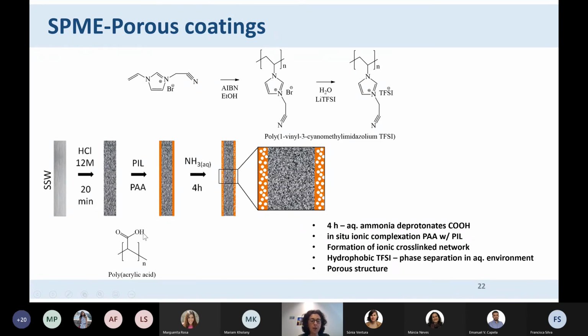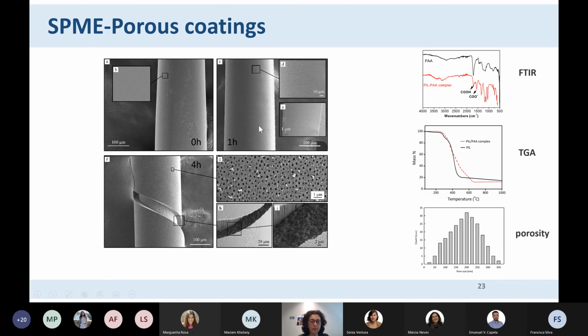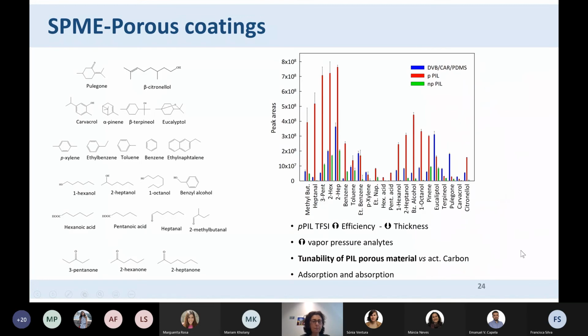And what we did was we ionized the polyacrylic acid, so it cross-linked with our PIL. And at the same time, the one that was not cross-linked was washed out by the solution, leaving us with pores. So here we have the different times that we had the wire coated inside of the ammonia solution. And only with 4 hours, we got the pores. So we have here the FTIR to prove that we have some carboxylic groups that are protonated, some that are not protonated, and here the porosity of our samples.